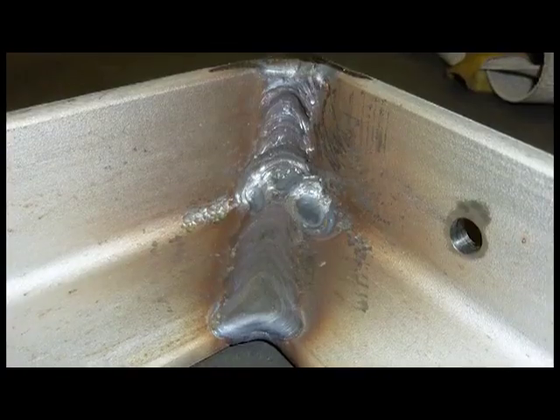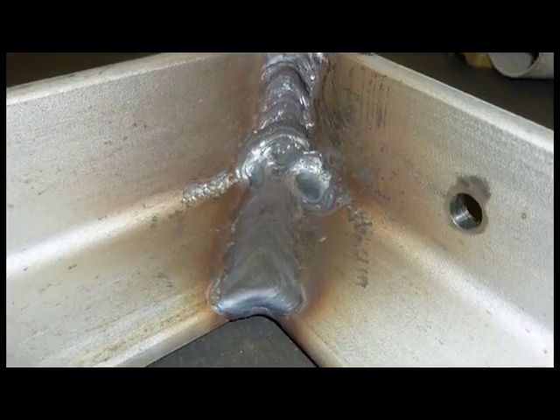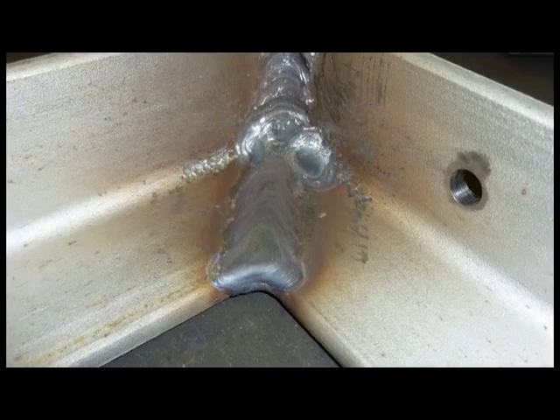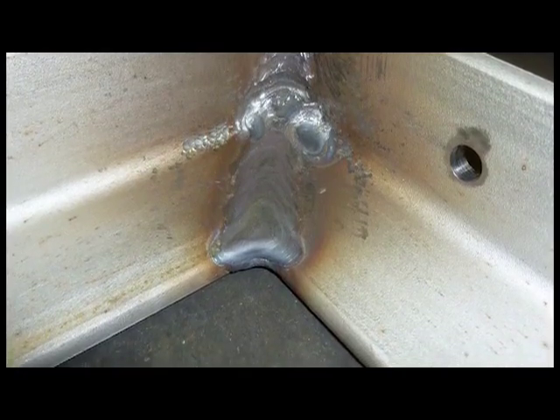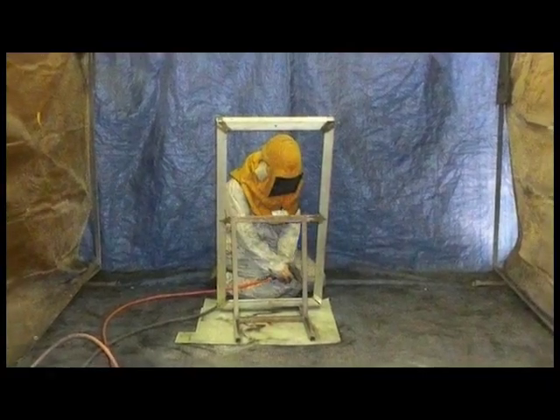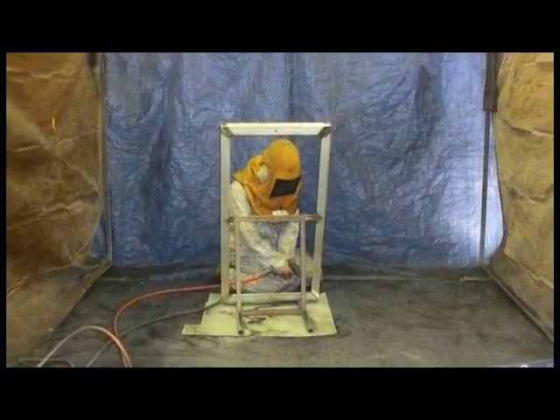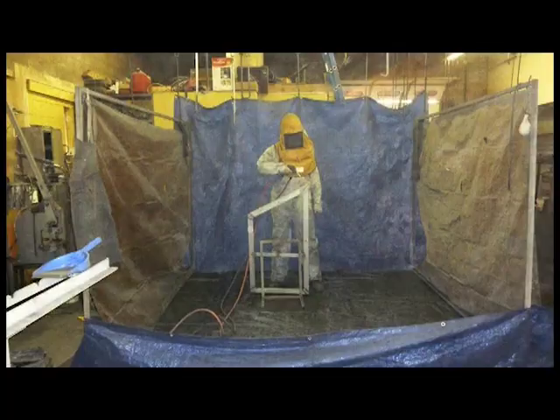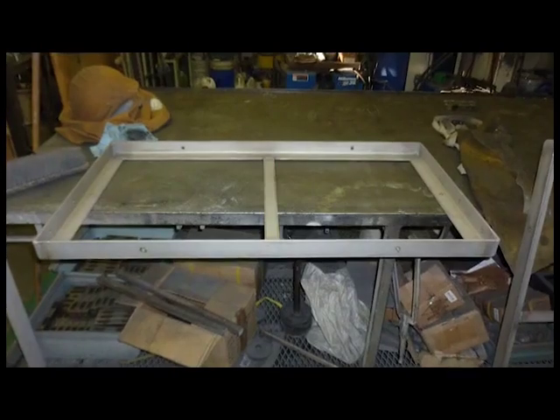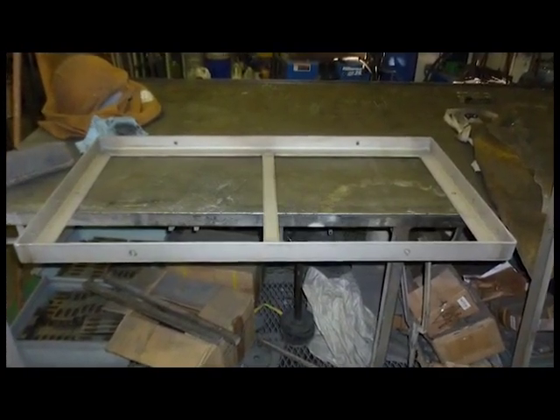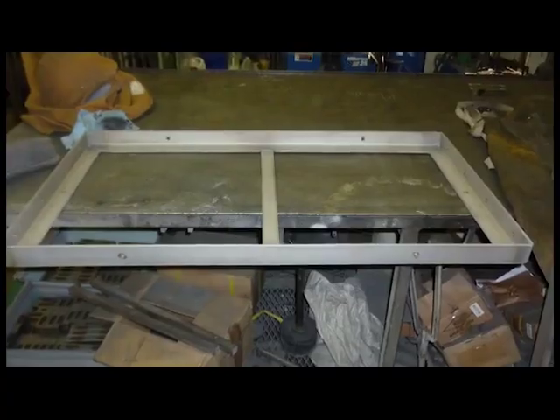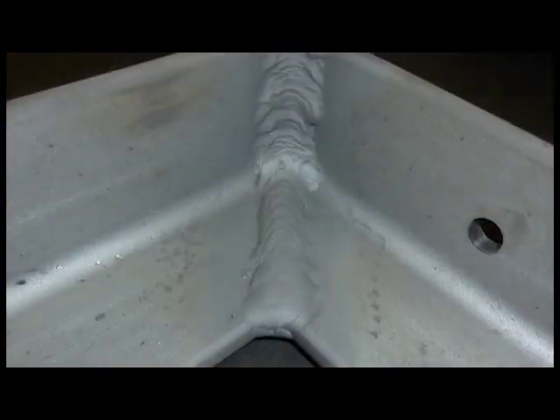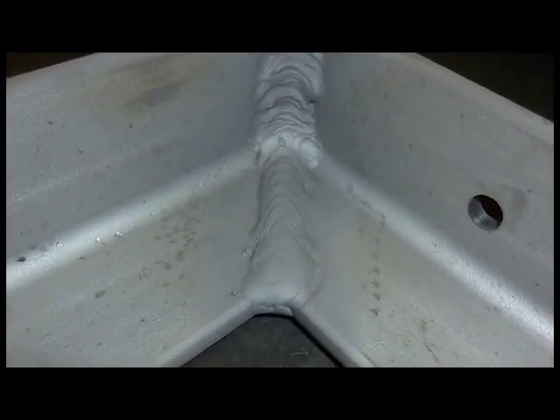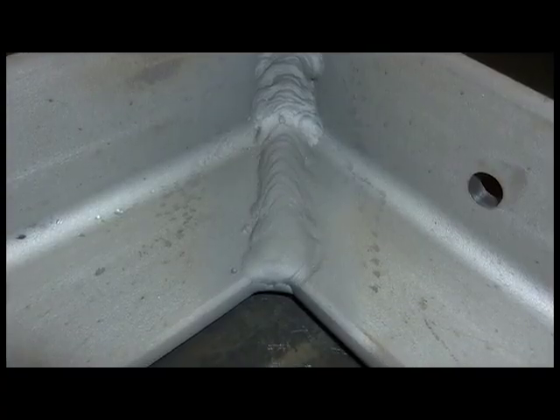The first step was to wire brush the smoke residue and chip the dingleberries off with a chisel. A more aggressive method was needed to remove the iron oxide coating, so the welds were sandblasted using aluminum oxide abrasive. The welds looked clean, but because the abrasive was recycled, the iron oxide residue left over in the abrasive smeared on the sandblasted surface.